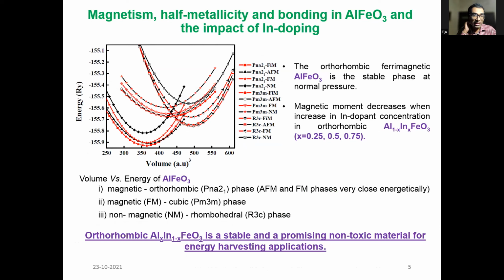So that paper was, in fact, completely computational work. Now, subsequently, we found that this material, not very surprisingly, but at the same time quite hearteningly, has a magnetic order, and its ground state is orthorhombic. And in the orthorhombic phase, it is magnetic. What does this mean? It means you can potentially leverage this when it comes to system deployment. On one hand it is likely to give Shockley-Queisser efficiencies, and on the other hand it is also very likely magnetic, which means it is plausibly useful for making photocatalysts that would be perfectly recyclable. Particularly so because ferrite surfaces are known to be quite stable. Next.